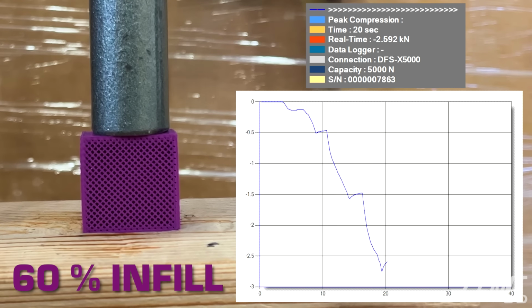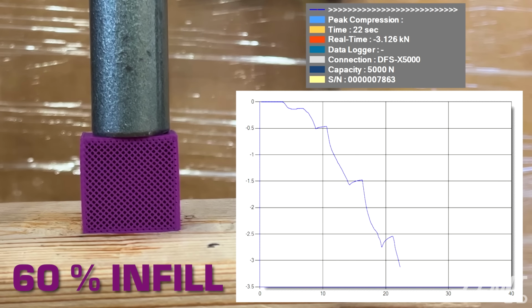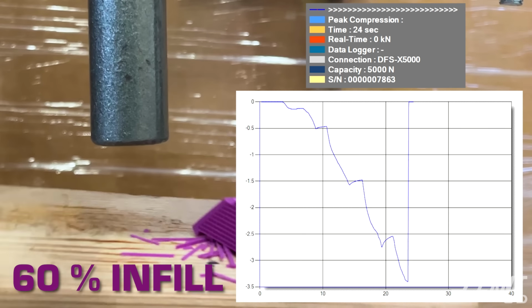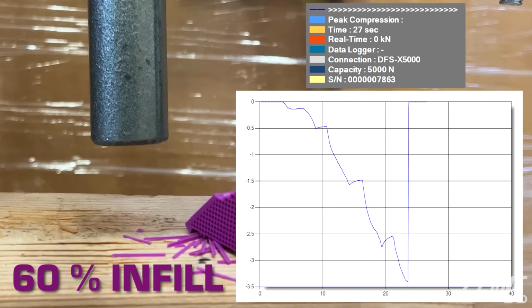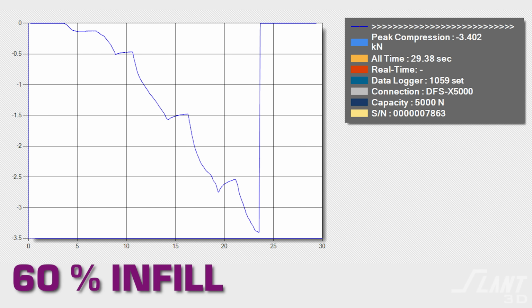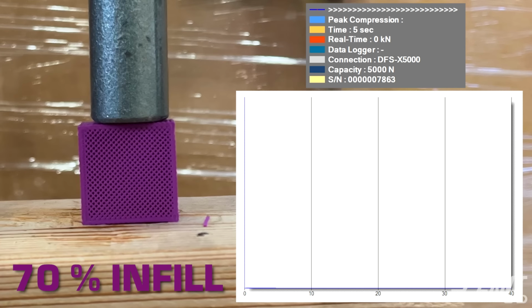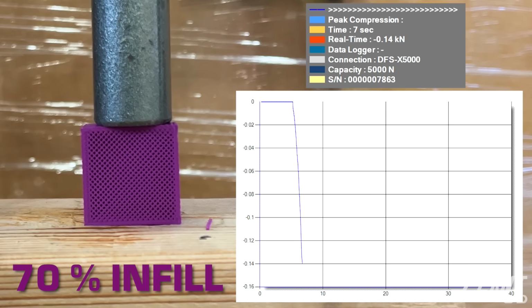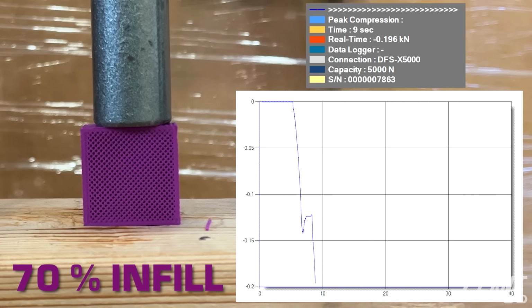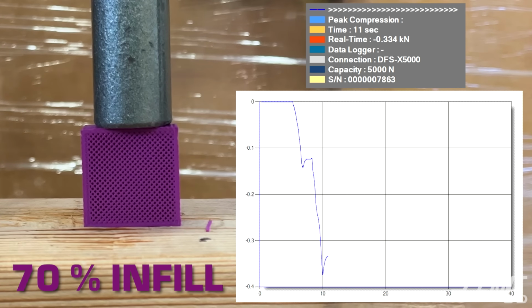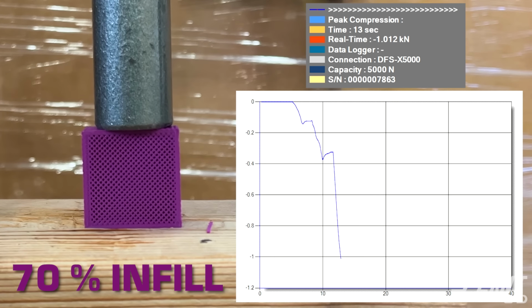There we are, passing the 60% infill mark already, and full catastrophic failure with debris around. A good amount of break, no hesitation on it at all, almost very little buckling, very solid all the way through until catastrophic failure at 3.5 kilonewtons. Now, moving on to the 70% infill, a good solid amount, very little air gap inside of there.